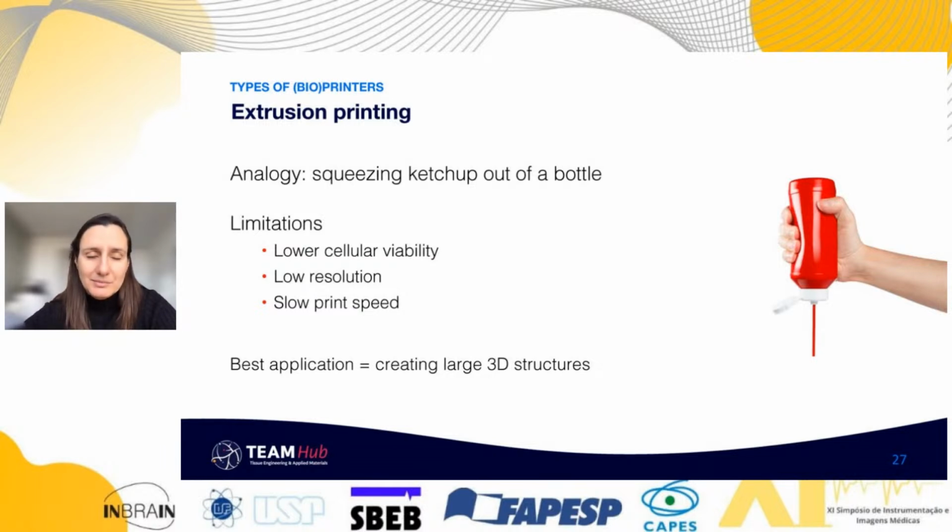But basically, imagine you have to squish the cells out of the syringe, out of the reservoir, and therefore you're applying a lot of shear stress on those cells. They are not going to be happy, and therefore the chances are you will have high cell mortality in that case. Generally speaking, this technology came a long way, but it's among the ones with the lowest